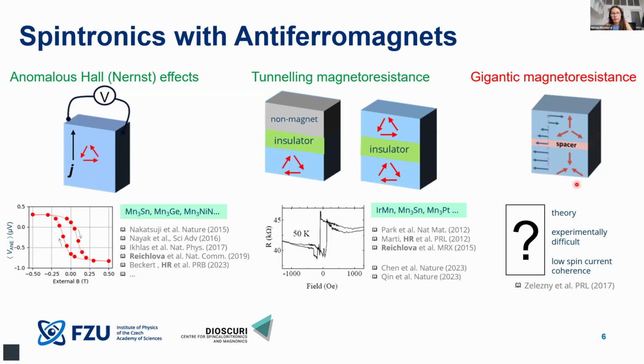However, experimentally, to my knowledge, there is no evidence of this giant magnetoresistance in antiferromagnets. And very often it comes down to experimental difficulties related to the quality or the perfection of the interface and to the relatively low spin current coherence, so that one loses the spin polarization which is required to get a measurable signal. So experimentally this part is basically missing. Now when I have these three effects next to each other, although not all of them were already experimentally demonstrated, nevertheless there is an amazing amount of work done and still ongoing.